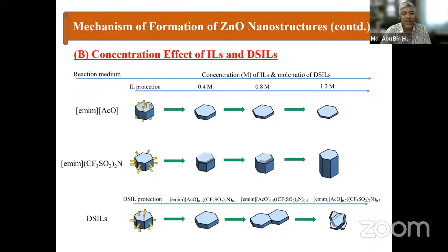So we can find the concentration effect here. So ionic liquid protection here, in this direction for this anion. And we can see that if we increase the concentration, the disc thickness becomes thinner and thinner. So it is thicker without ionic liquid. And for this one, this is becoming rod-like, longer and longer, because the control is now along this direction, and along this direction the diameter does not change. And for double salt ionic liquid, since there is control from both directions, we have a structure in between like this cluster, and ultimately they become interpenetrated discs.